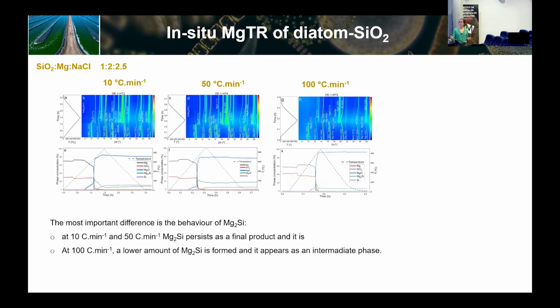So then we also changed the rate, and we can see that if the rate is very slow, the magnesium silicide that is an intermediate will become a reaction product. And if the heating ramp is very fast, then it will just be an intermediate.